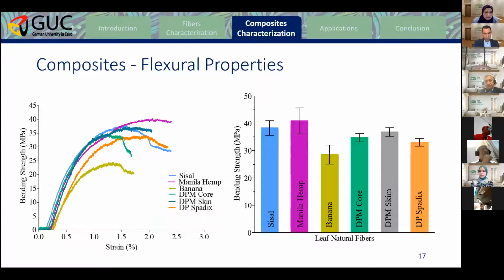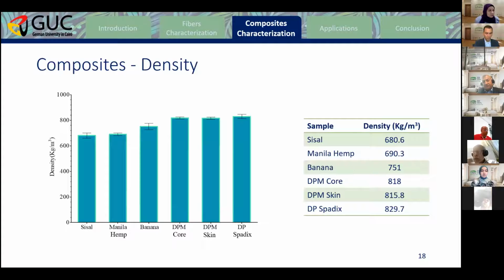When we compared the date palm midrib, either core or skin, to the date palm spadix composite, we found that the bending strength of the date palm spadix is somewhat lower than the other values, and this could be because date palm spadix is composed of pure fiber bundles, so it's flexible, which makes its bending strength much lower. For the composite density, the samples were within the same range with a slight increase in the date palm values.